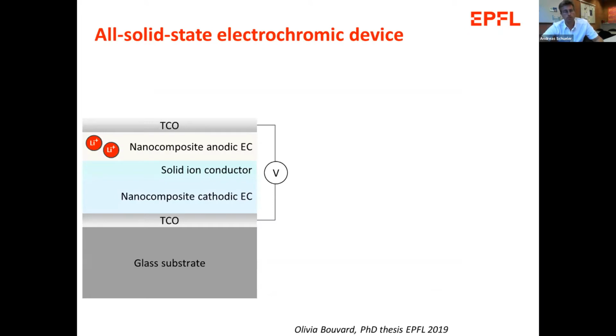So how would this work? We would start with a glass substrate. That would be shown here. We would deposit a first transparent electrode here, a transparent conducting oxide. Then we would put a nanocomposite cathodic layer here. We would put the solid ion conductor, and then an anodic electrochromic layer again, and we need a top electrode, which again is transparent. This looks very much like a thin film microbattery.